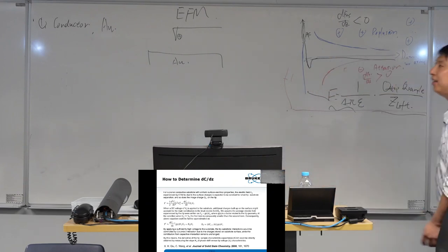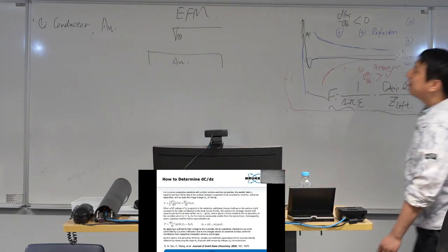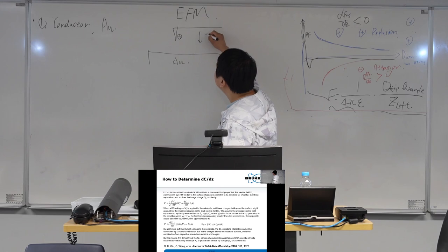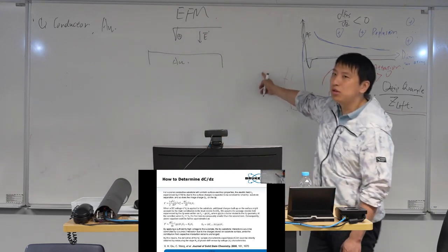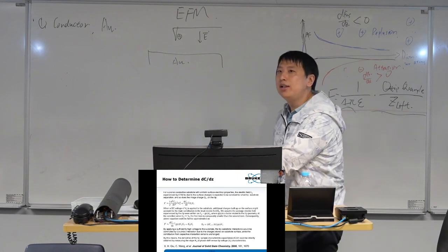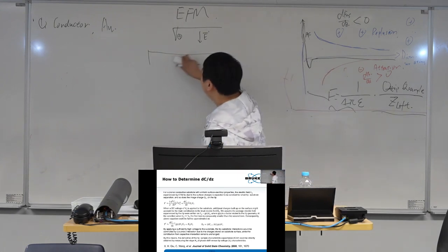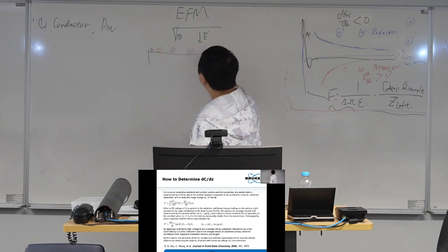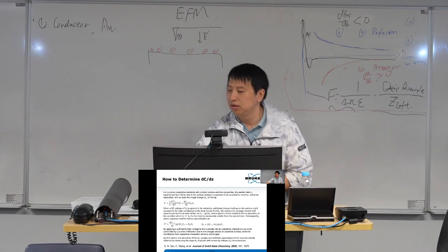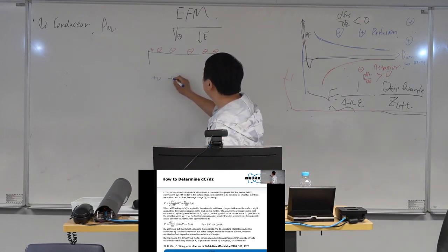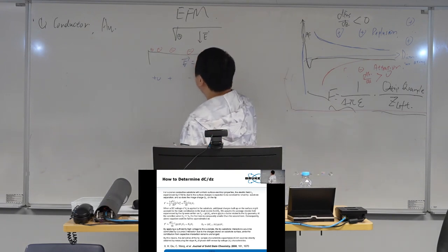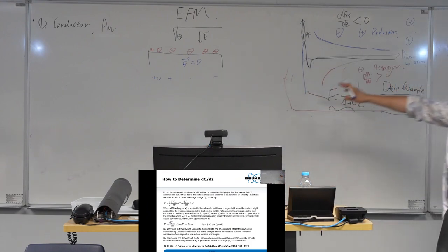What will happen? As we explained at the beginning, this probe is playing as the source of electric field. This electric field will polarize the gold, and after polarization, the top of the gold will be negative charge, right? And the bottom of the gold will be positive, and inside the gold, the electric field is 0. That's the electric shielding, okay?